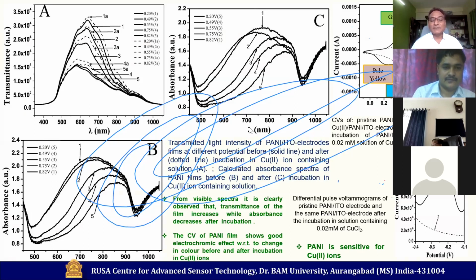Moreover, from this visible spectra, it is clearly observed that the transparency, the transmittance of the film, increases after incubation. And this is the CV before and after incubation, and we got wonderful electrochromic and electrochemical response. You can see the color changes before and after incubation. Later on we tested it for detection; this is the differential pulse voltammogram for copper.